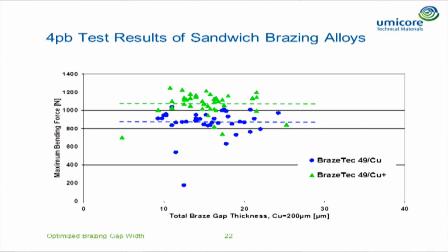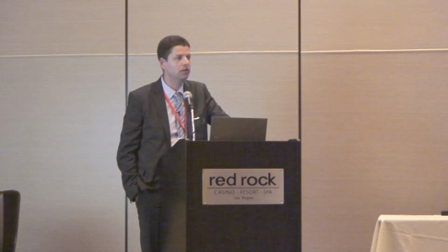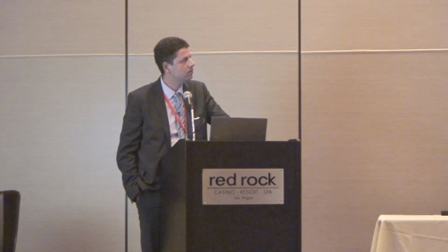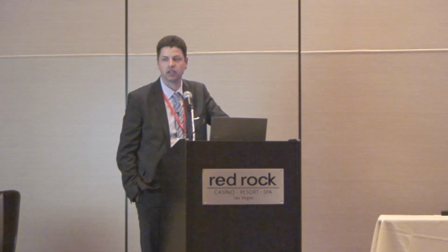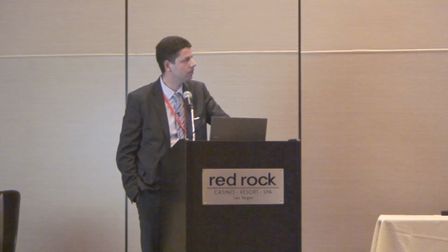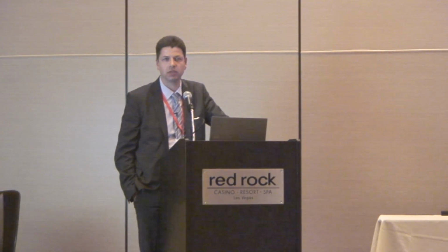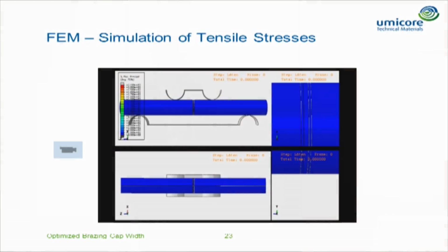So one is the normal pure copper, and we use the 49/Cu+, which has a modified copper layer with a higher strength. And this higher strength, which we can see in our shear test, we can also see now in the 4-point bending: the average strength of the parts brazed with Cu+ is approximately 25% higher than with the other one. But for the gap size, we cannot see any big influence. So these are now the results for the parts.